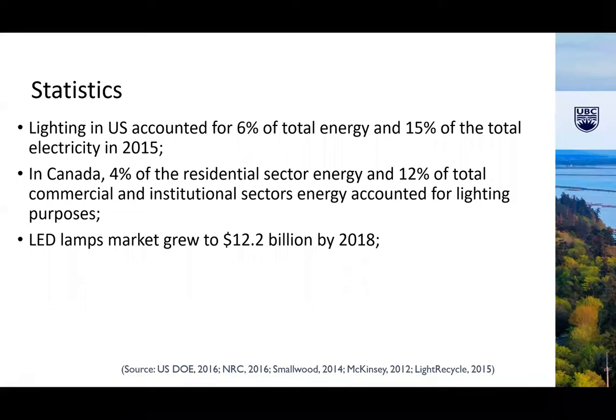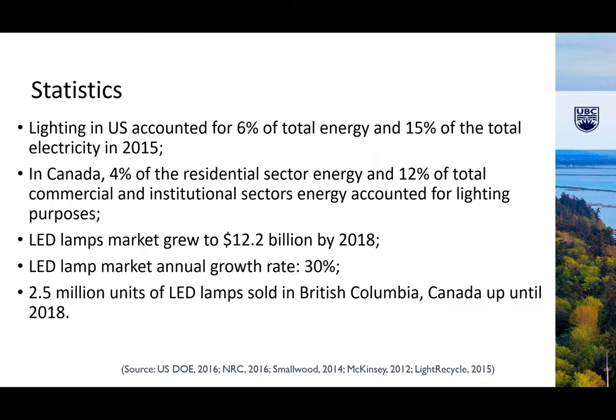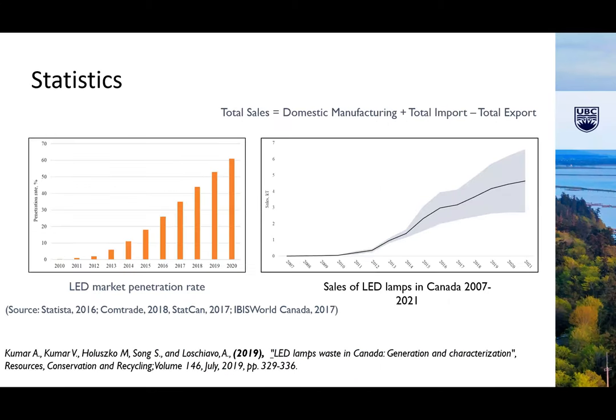When we look on the other hand at the market, it grew obviously, and we have annual growth of 30%. So even if you compare those e-waste statistics, it's staggering. Compared to 3 to 4, now we're growing 30%, and 2.5 million units of LED were sold in British Columbia in 2018. Wonderful. This is all good, except that we don't have the recycling process for these lamps. The recyclers, the company that we've been collaborating with on this project, recycle 90% of all lamps in BC, but they were stuck because they just kept getting all their e-waste without having proper equipment to recycle. So again, looking at statistics, it will grow, and it's the best solution in terms of energy saving. And as we can see, it will continue to grow.